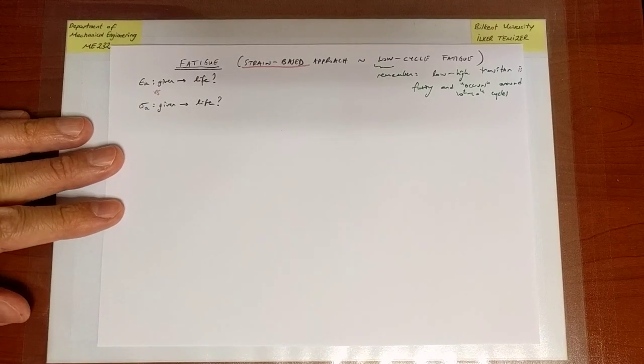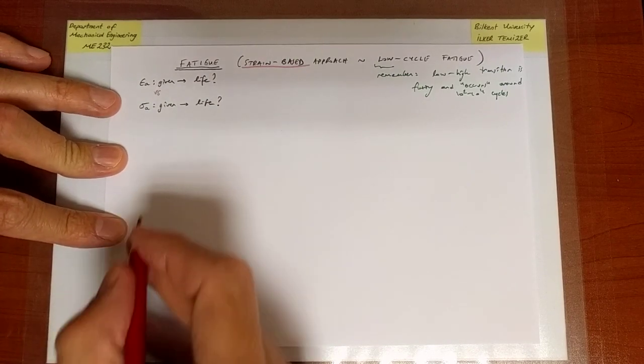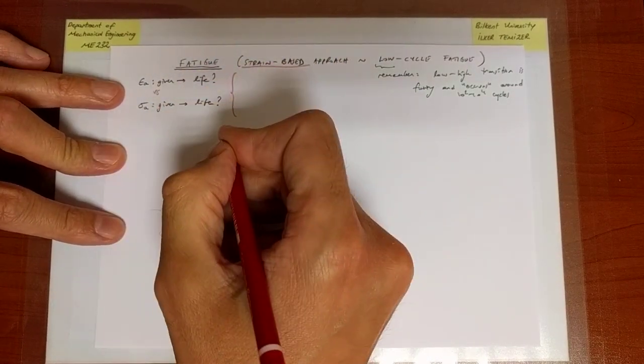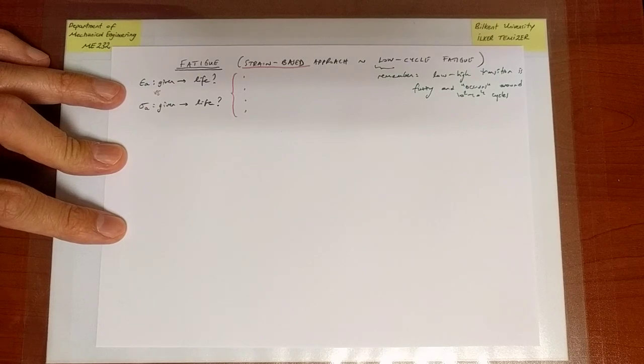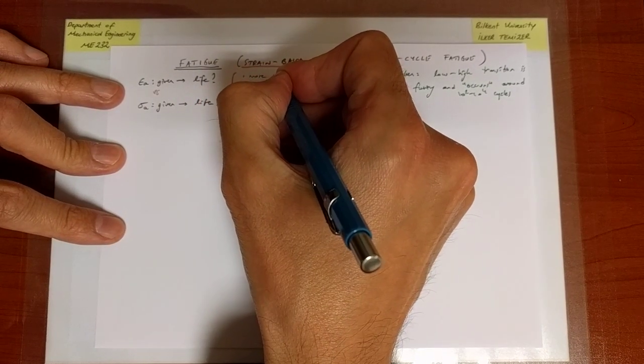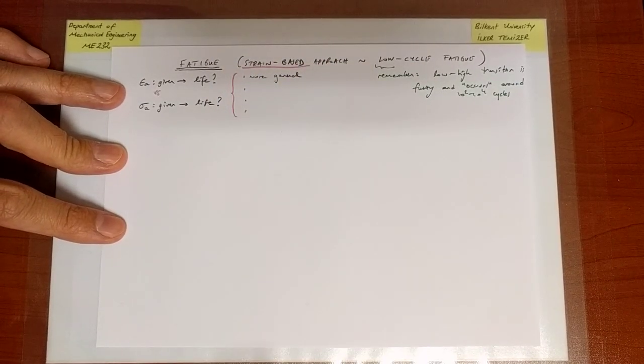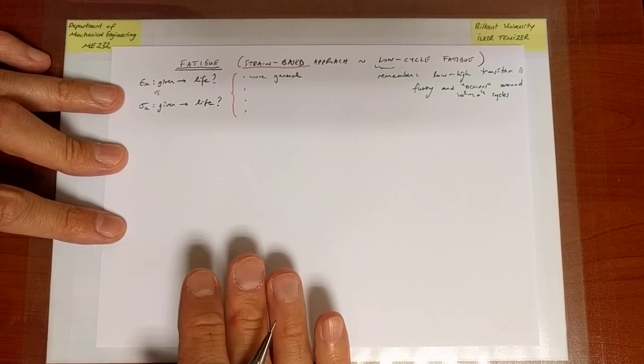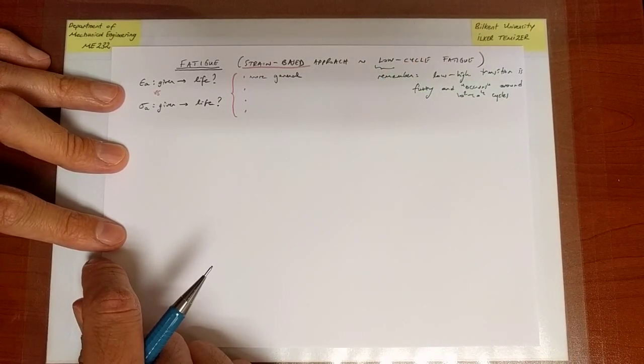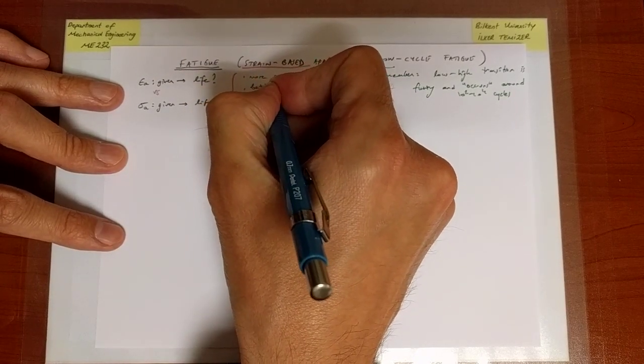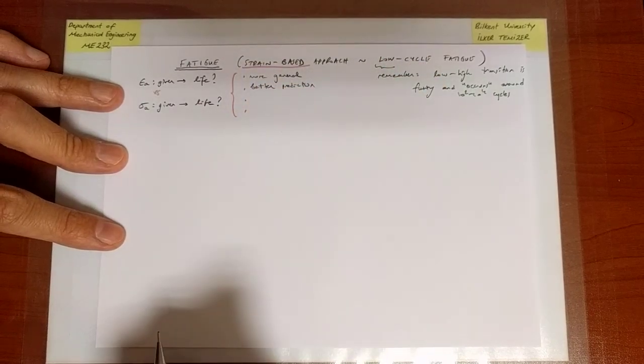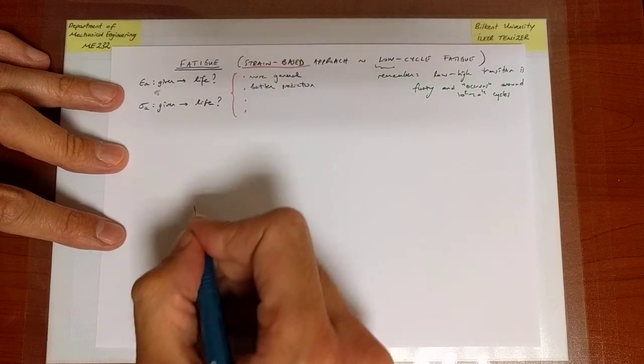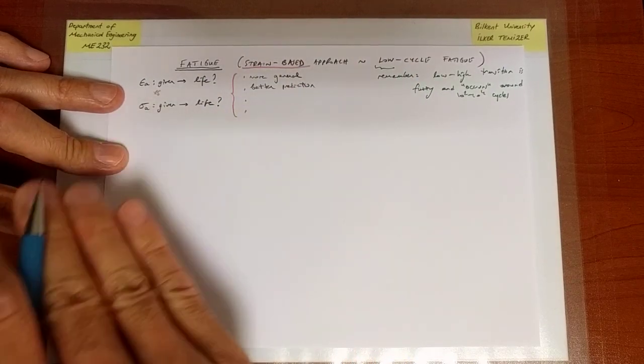But now we're going to pose an alternative way of framing the fatigue problem, the strain-based approach, which has, compared to the stress-based approach that we've discussed so far, a series of advantages. And let us state here 4 advantages. The first advantage is that it turns out it's a bit more general, in the sense that it has the potential to apply to the high cycle fatigue regime as well, although its strength is predominantly in the low cycle fatigue region. Moreover, it can make better predictions, again especially in the low cycle fatigue region, where one can imagine that perhaps the Basquin equation may still be employed, but the strain-based approach, it turns out, can do a better prediction in the low cycle regime.